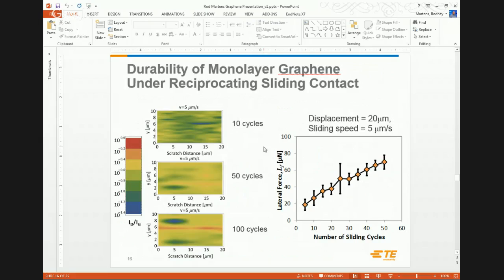Well, in this slide, we're showing the 10 micronewton load at 10, 50, and 100 cycles. See that we're introducing more and more defects. So red would indicate that we've got a lot of defects in the film. Also, what's interesting is the frictional force is going up as a function of cycles. And this could be a couple of things going on here. It could be that we're bunching the graphene up ahead of the tip, kind of like bunching a rug up. And additionally, it could be that we're wearing a trough into the silicon as well, so we're getting a little bit more contact area, which would be higher force.